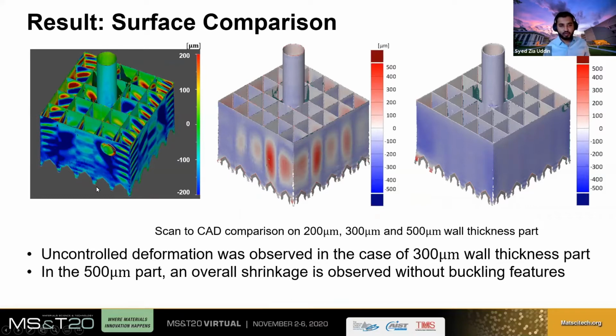On the left, we have a 200 micron wall thickness part, which is fabricated and then compared against the CAD model. As we can see in the contour plots that show the deviation of these parts, we see a lot of in and out of surface buckling or large deformations with a very high frequency and magnitude. In the middle, we see the 300 micron wall thickness part compared against its CAD counterpart, and we see there are large bumps, and also some large deformation and buckling. But one thing to note is that the frequency of buckling is much less in the 300 micron wall thickness part than observed in the 200 micron part.